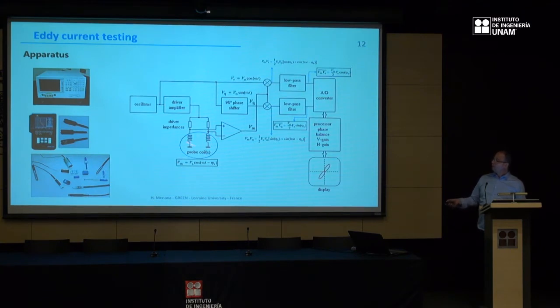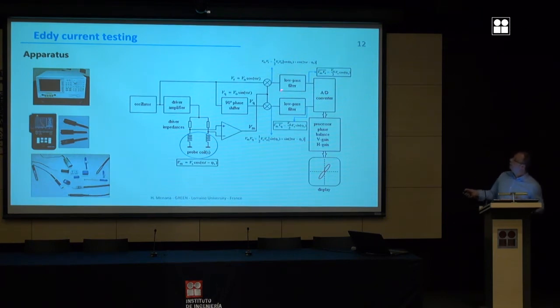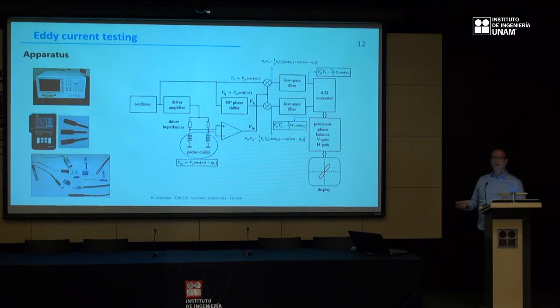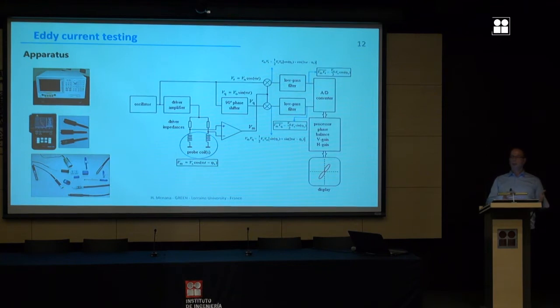You sense the difference here, as a differential sensor is put there, a differential coil. You sense the variation of the impedance, then you make a product of the measured signal with the reference, and the reference shifted by a quarter of a period. So you get these signals here, this one and this one. You put them through a filter to remove these parts to keep only the mean value. So you get the active and reactive part, real and imaginary part, if you like, and then you display it in an impedance plane.